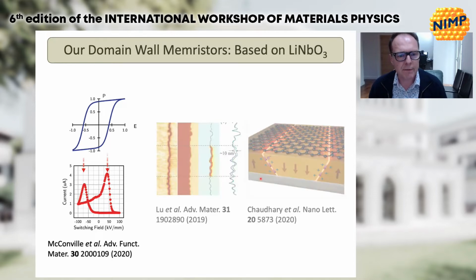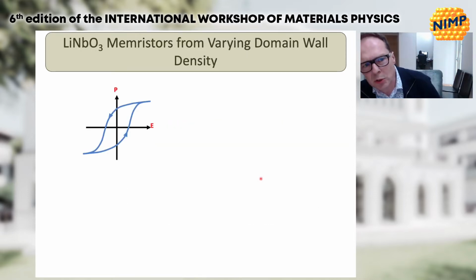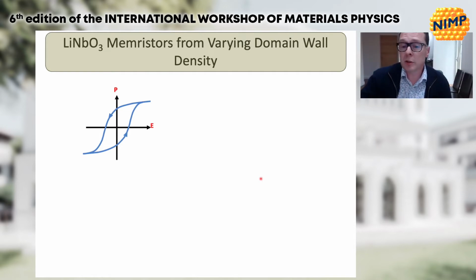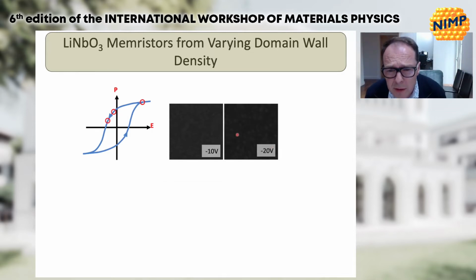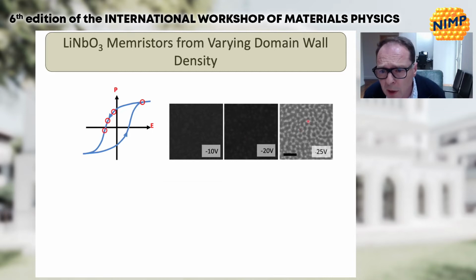Okay, so first study first. This is dead easy. So we have a lithium niobate single crystal thin film. We have a top electrode, a lower electrode. When you have no domain walls straddling the interelectrode gap, you get no conduction. As soon as you start to cause partial switching, in other words, you start going around this polarization loop, you change the microstructure. And I don't know how the contrast is here, but you start to develop reverse domains. And obviously then you get these circular domain walls that delineate the boundary between these 2 polar orientations.